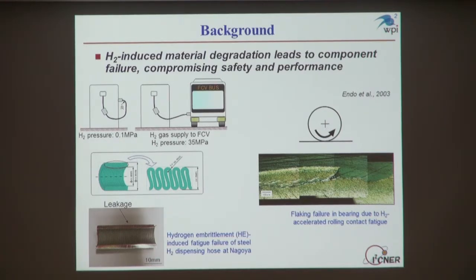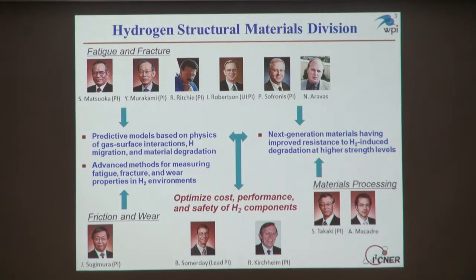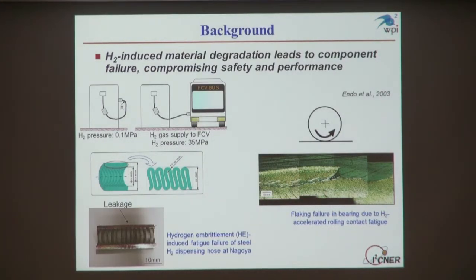The first I wanted to show you is a failure of a hose on a hydrogen dispenser at a fueling station. This flexible hose was being subjected to pressure cycles, hydrogen gas pressure cycles. Under the action of these cyclic stresses and the presence of the hydrogen, this hose experienced a failure, which led to hydrogen being released, which is a concern because hydrogen is a flammable gas. This was an example of what we call hydrogen embrittlement-induced fatigue failure.